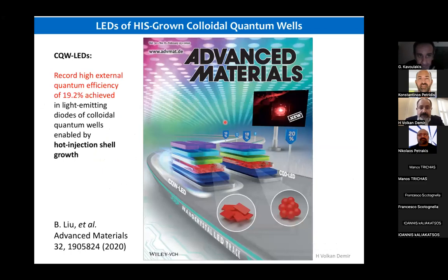The same material, so again, highly engineered for the reasons I explained, but now a different use. And this is in a LED structure where we electrically directly drive these emitters. And we were interested in seeing high efficiency, and this was 19.2% at the time. These are the hero devices, the best values we could measure using the same colloidal quantum wells, again, based on hot injection shell growth, as I explained thus far, but having fully conventional structure.